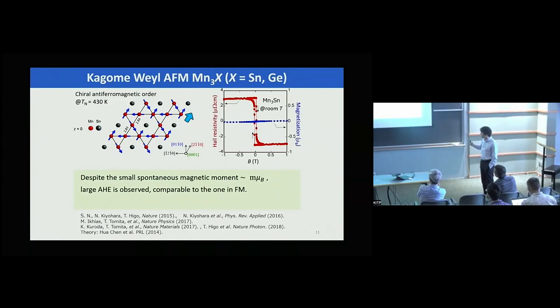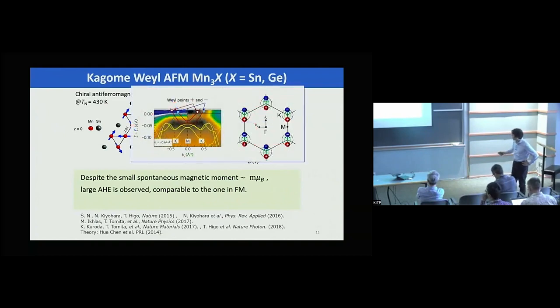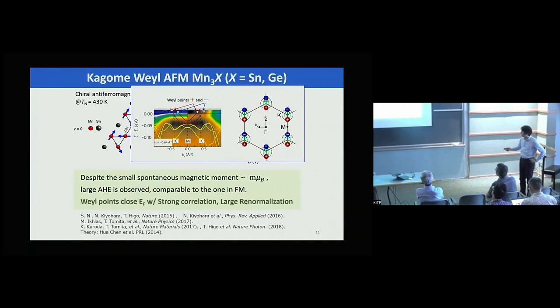Because of the geometrical frustration, it has 120-degree order. It's not a simple 120-degree order; it's anti-chiral, the vector chirality is negative, leading to a very tiny magnetization of the order of milli-μB that cannot be seen in this normal ferromagnetic domain, in this unit of magnetization in μB. Instead, the Hall resistivity is very large, comparable to the one in a ferromagnet. If we do ARPES measurement, we found the Weyl point near the hexagonal Brillouin zone K point, and not only just the Weyl point, but also the band itself, which produces the Weyl point, turned out to be strongly renormalized.